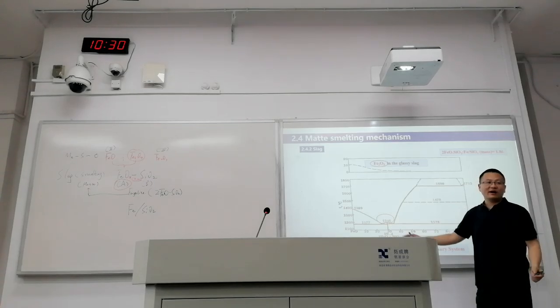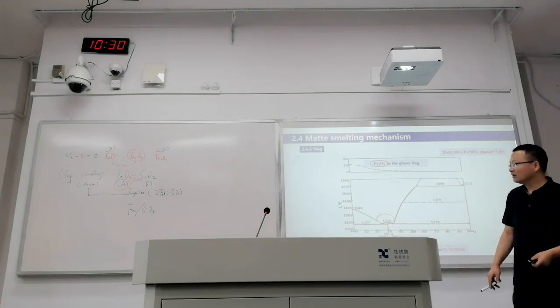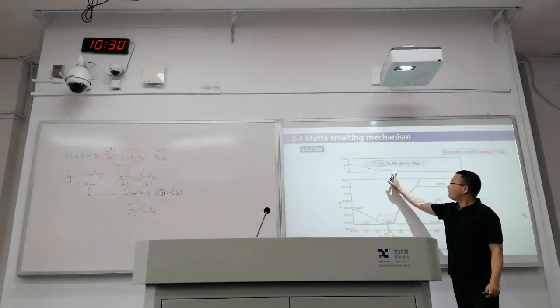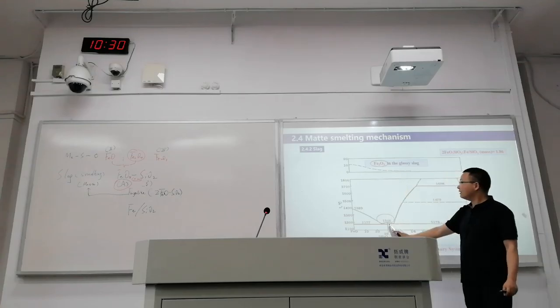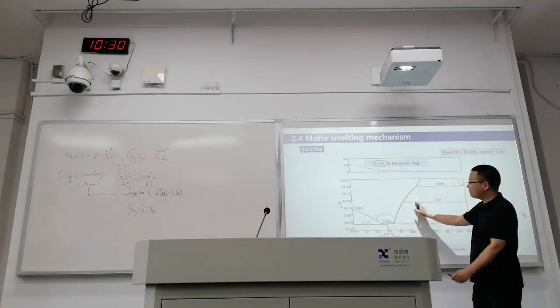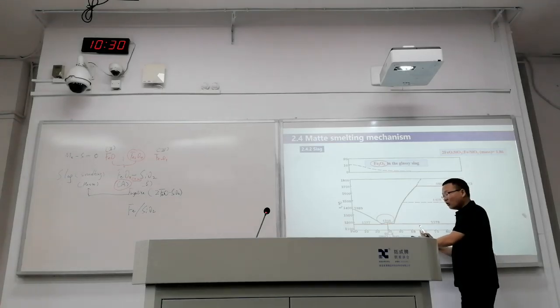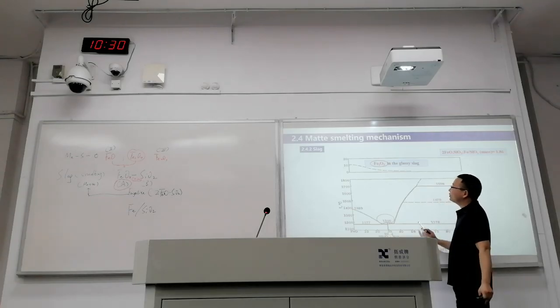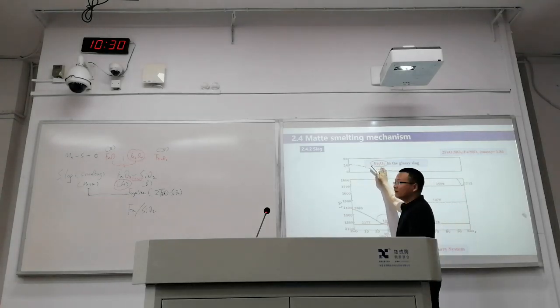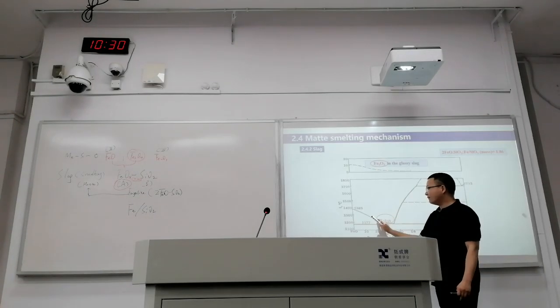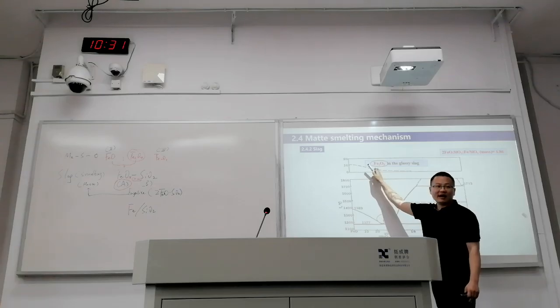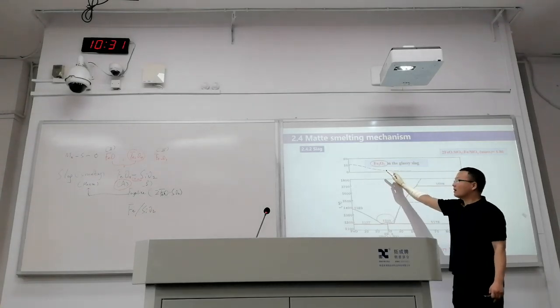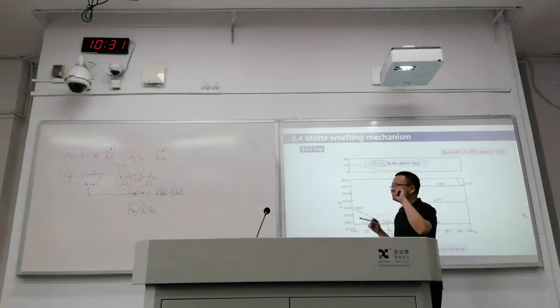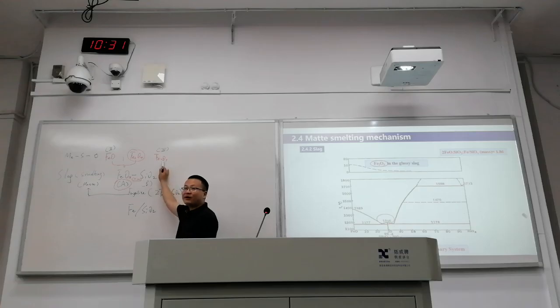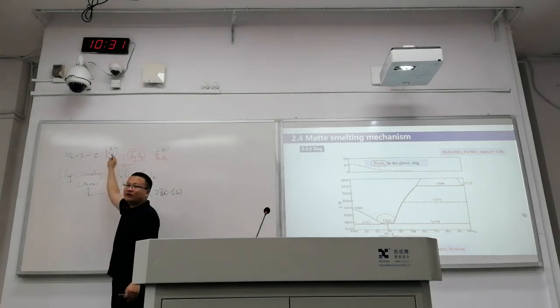It's very interesting. Actually, when I was having such thinking some 10 years ago, if we are reading the figure upwards, what are we finding? If we are starting from this side, and we are decreasing the amount of silicon oxide, or increasing the iron to silicon ratio, we are having ferric ions. If you are in value 1, you are having a larger amount of ferric ion. And if you are in value 2, a very small amount of ferric oxide. So when there is a very small amount of ferric ion, you are having very little magnetite. So we are having dominant ferrous oxide.